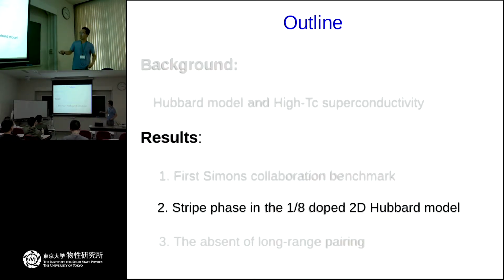The second part of the result is about the stripe phase in the 1/8 doped two-dimensional Hubbard model. As I just mentioned, at 1/8 doping there is a very large discrepancy among different methods. If you have done a simulation of the Hubbard model before, you will know 1/8 doping is the hardest doping for simulation, which means if you do quantum Monte Carlo, the average sign for this doping is the smallest. And if you do DMRG, the entanglement entropy at this doping is maximum.